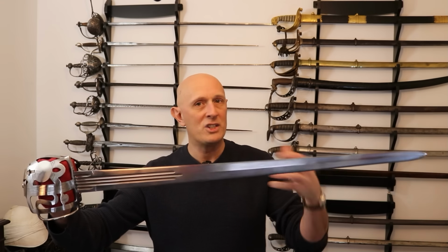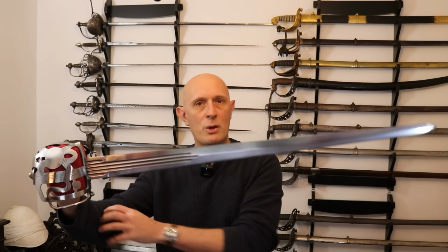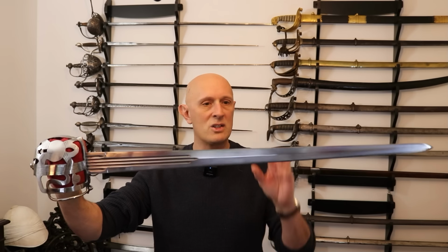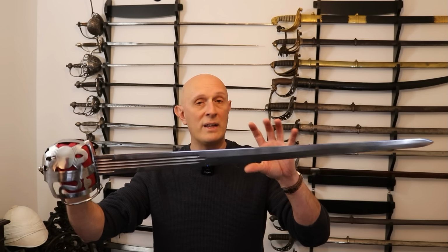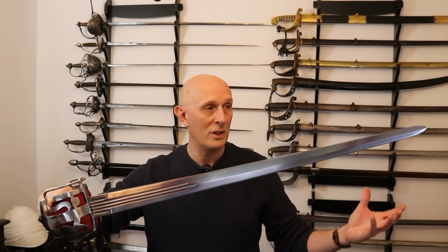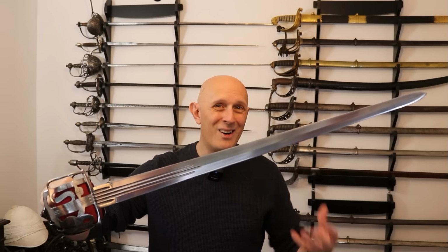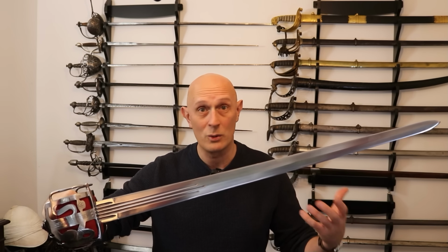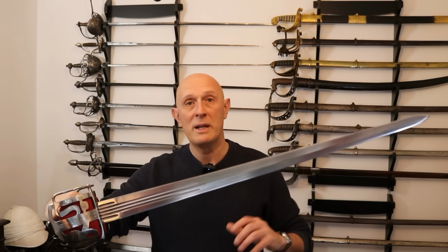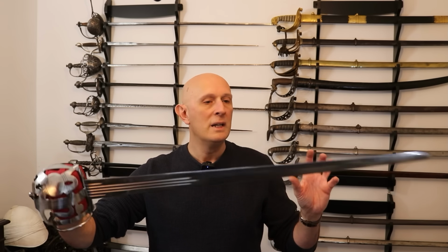If the blade's bent, I straighten it, okay? Whereas this blade here is a bit softer at the edge, doesn't have such a hard edge as the edge quenched Japanese or Indian sword might do, so slightly softer at the edge because we want to maintain the toughness. We're not going to quench this as hard and as brutally. For example, Japanese swords are quenched with water, European swords usually quenched with oil. So a softer edge, but a springy body.